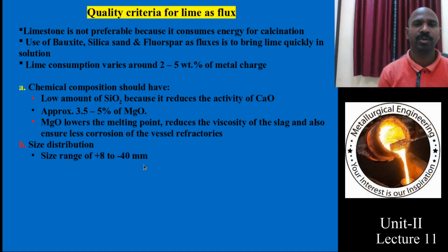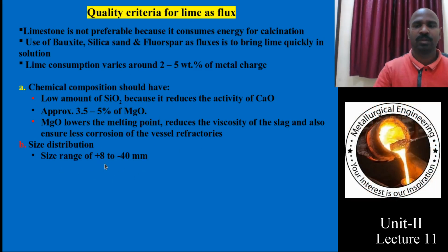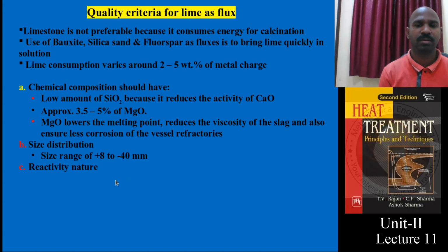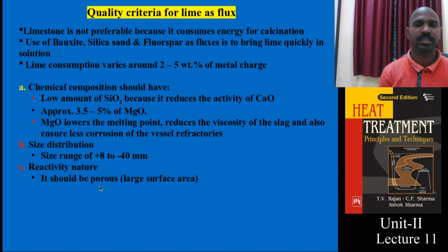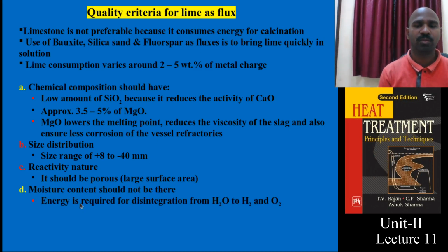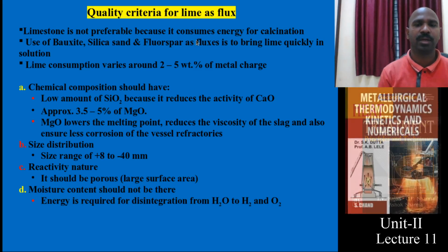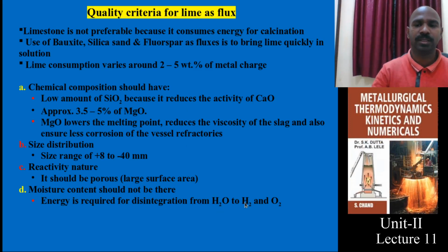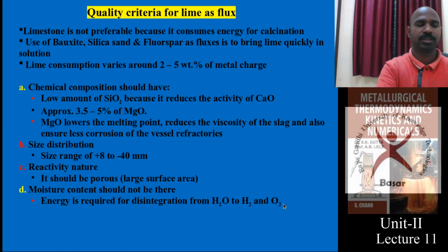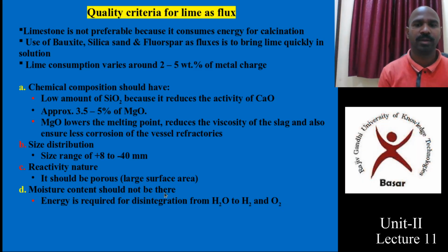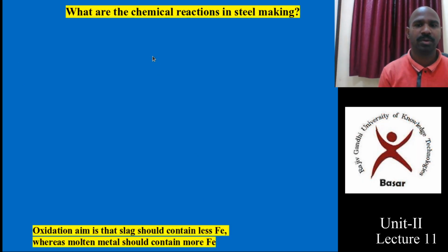Regarding size distribution, the lime preferably used has a particle size of 8 mm to 40 mm. For reactivity, the lime should be porous in nature and free of moisture. It should have less moisture content, because if there is moisture, it needs to be dissociated into H2 and O2. That is why it should preferably have less moisture content.